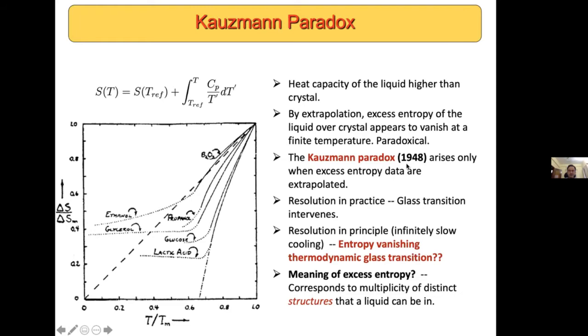And this only arises in reality when the excess entropy measurements one has are extrapolated, because invariably before you reach a point where this excess entropy is vanishing, the glass transition intervenes. So that's the resolution in practice of the Kauzmann paradox. But one can ask the question, if one does in fact continue along this excess entropy curve in equilibrium by waiting longer and longer and longer, what happens eventually? So the resolution in principle that has been offered, and it's sort of a question mark at this stage because other interesting things can happen in between, is that there is some kind of a thermodynamic transition in waiting where the excess entropy vanishes.